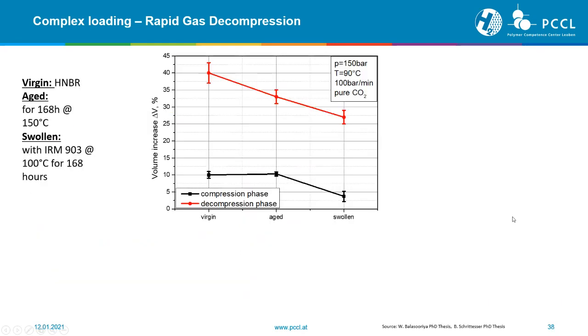However, when you think a little bit more into detail, I've brought you some examples with me of virgin material, of an aged one, thinking of the impact of time, thermo-oxidative aging. And then also additionally, I've brought with me a swollen result, where we've swollen our samples with an IRM 903 at 100 degrees for 168 hours. Result of volume increase during compression phase and during decompression: what we found so far is for virgin one, roughly 10% during compression, 40% during decompression. For the aged one, we have also 10% volume increase during compression, 30 to 35% during decompression. And for the swollen one, we've observed lower volume increase during compression and also a much lower increase during decompression.